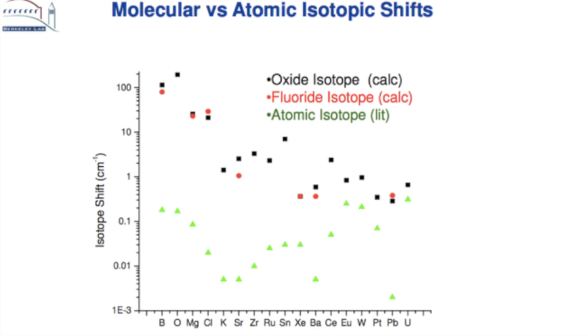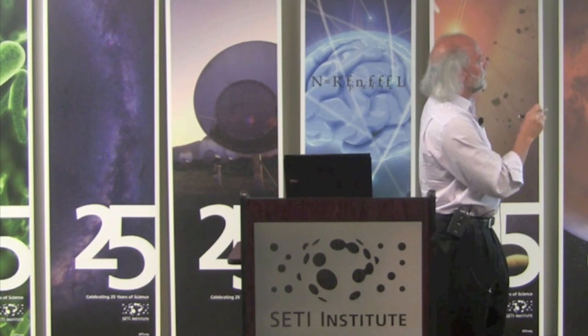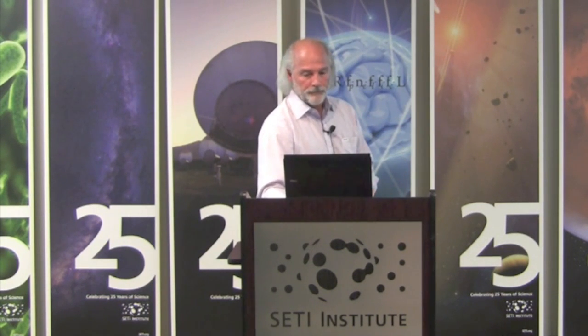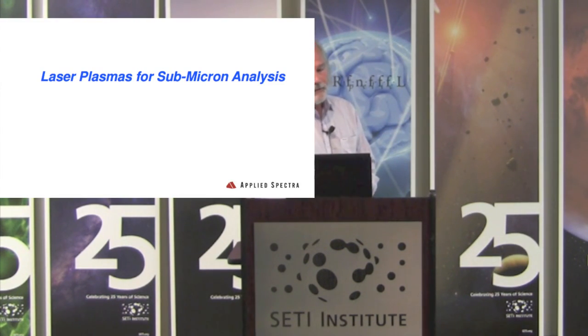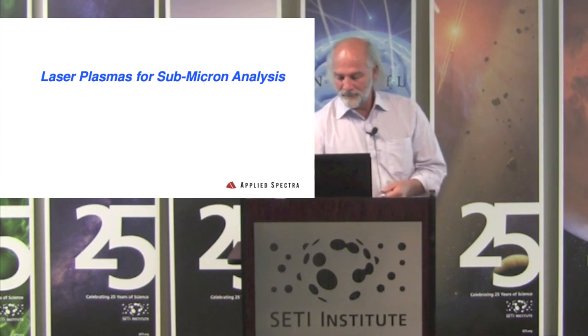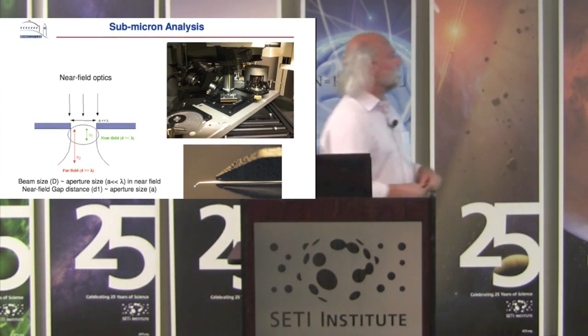But this is a log scale. This is what we calculate when you're looking at the oxide or the fluoride that forms in these plasmas versus what Livermore said, that according to theory, you should see from atomic transitions. So this opens up a whole new realm of doing isotopes now with LIBS plasmas, several orders of magnitude, especially for the lighter elements. Okay, enough about isotopes. I think I beat the heck out of that.